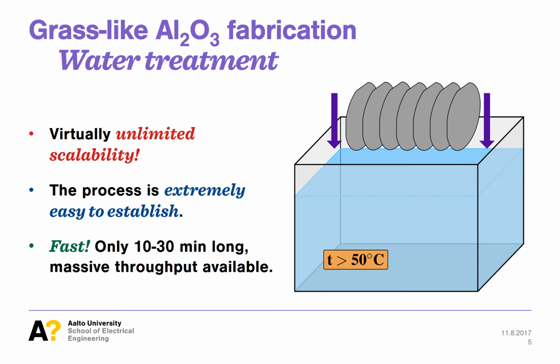For example, we have found that 30 minutes is not enough to transform a 100 nanometer thick film into a nanoporous state completely. The transformation is activated at the surface and progresses into the film depths over time, which allows some play with the processing time to achieve an interface of ALD-grown and porous film. However, we did not use this feature in our anti-reflective coatings.